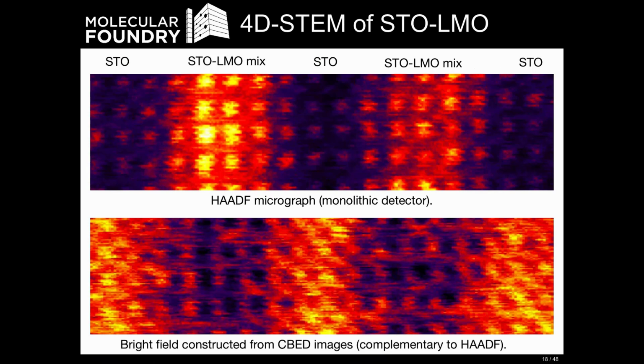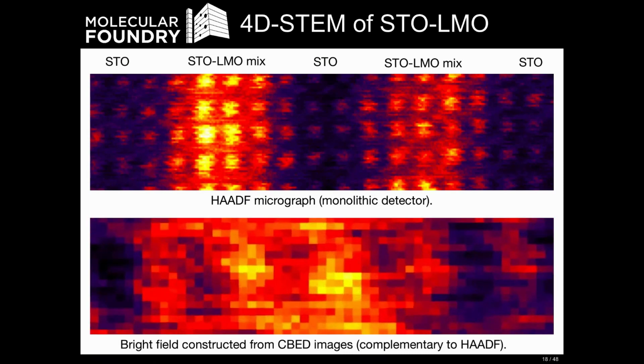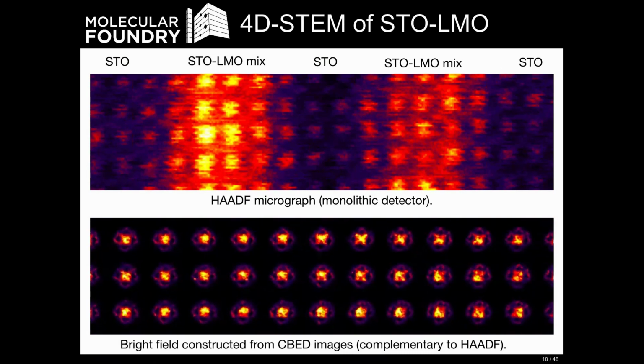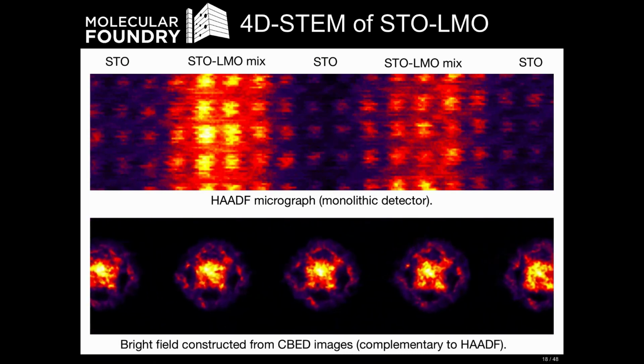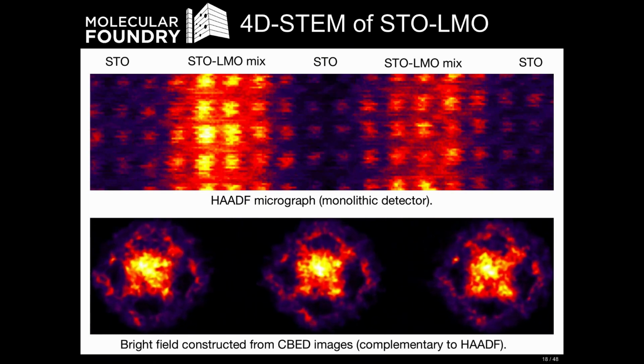The difference between the top and the bottom is that although the top has bright contrast on the A sites and a little bit of contrast on the B sites, and the bottom has dark contrast, they're roughly complementary. The bottom image has a full diffraction pattern under each pixel. These patterns contain all of the local scattering information, the scattering cross sections. So if we have a good enough simulation, we could work out the thickness and the composition, for example. And that's what I'm going to show next.